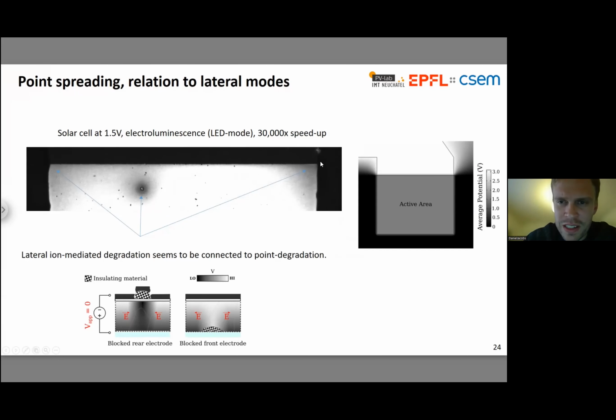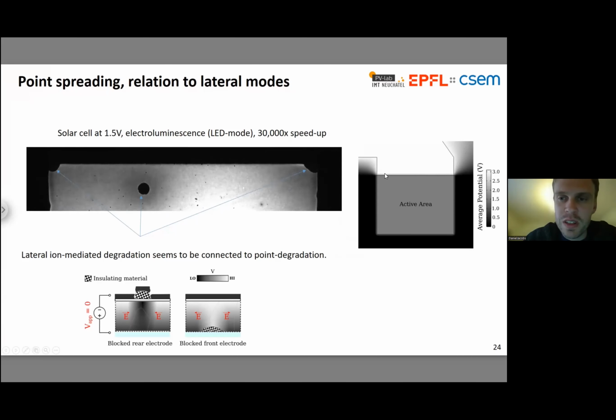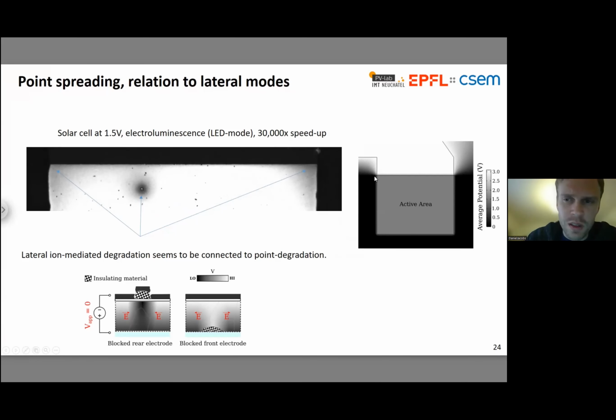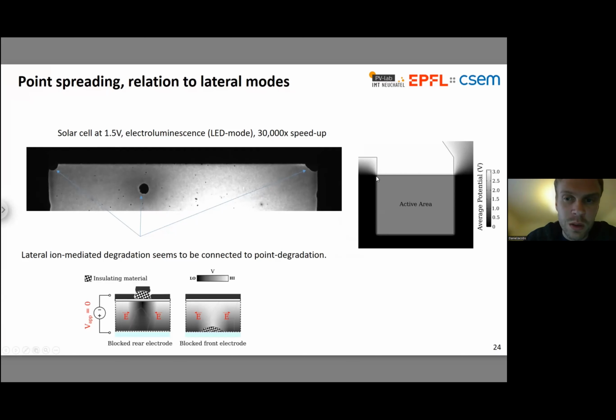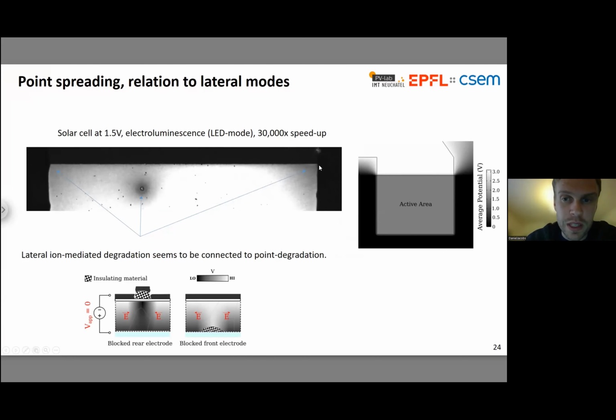It's very hard to understand that as being a point of vulnerability, except if we're thinking about lateral ion migration. As you can see in the figure on the right, these corners are regions where we have quite strong lateral electric fields, which means we can expect fairly strong fluxes of ions around these corners. I think that's the only really plausible way of explaining why they would be the weakest links in the degradation that we see here. But then it's very interesting that it resembles the point degradation.